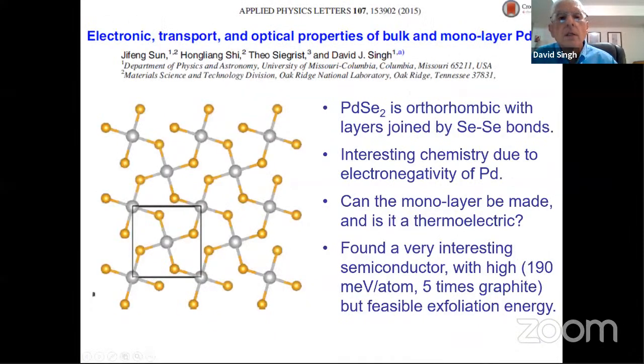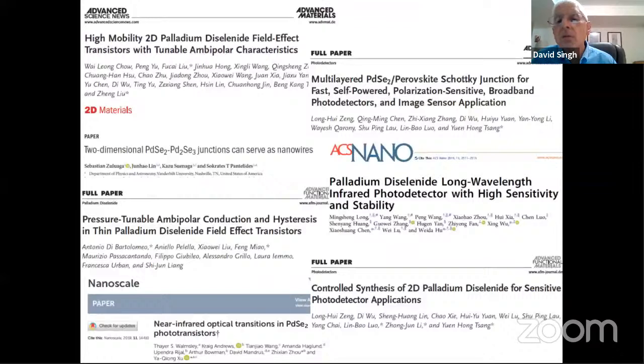All right. This is some other material that we identified. This is monolayer palladium diselenide. It was an unknown material, but we predicted that. And we found it was interesting, not so much for thermoelectric, but we studied it because we thought it might be an interesting thermoelectric, but then people made it. So I just want to have this, and they find it very interesting for other applications. So you can predict things, and nowadays experiments are good and they can make things, and sometimes you get lucky and this stuff turns out to have some use.